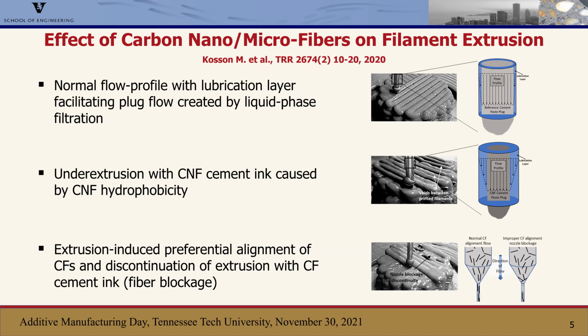Another consideration when you're using larger fibers, such as the carbon microfibers we're using here in this bottom image, is that they will have a tendency to preferentially align with the direction of the extrusion. But if they don't preferentially align properly, which is prone to happening occasionally, you can see a blockage in the fibers and have occasional printing discontinuities, such as this picture here on the bottom.